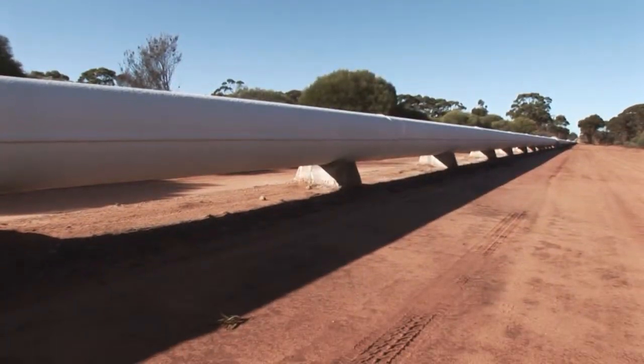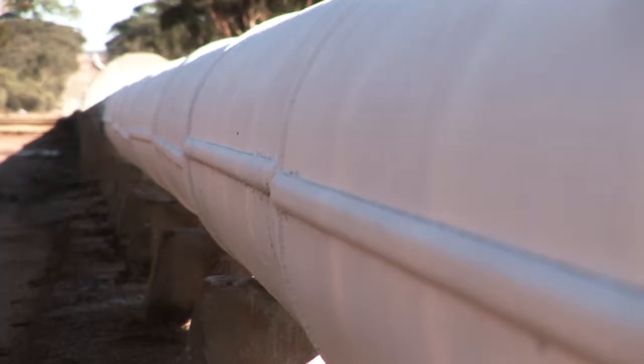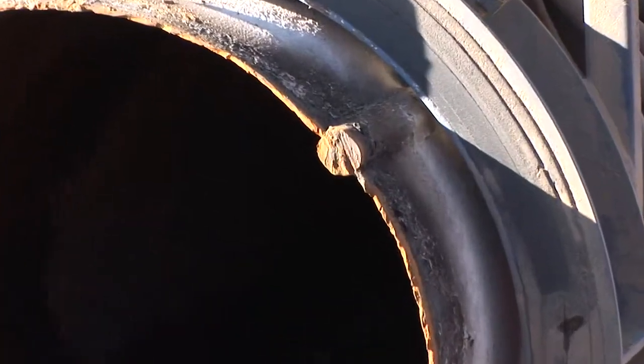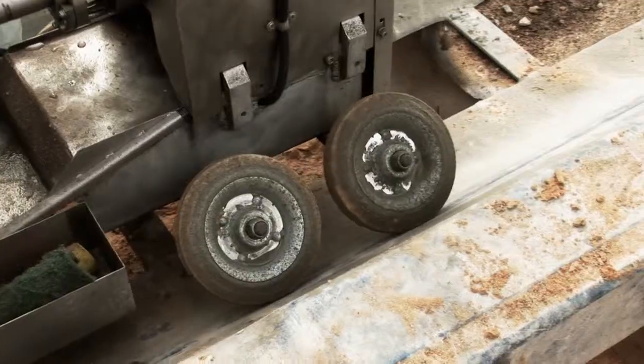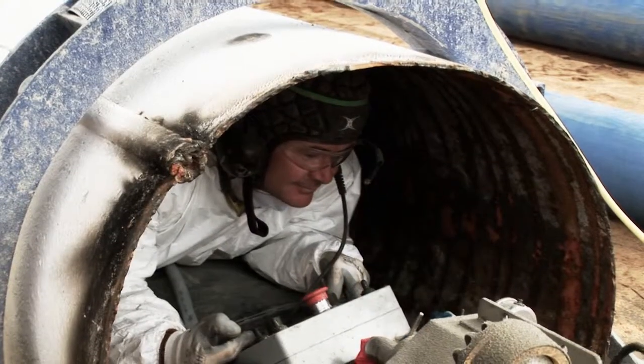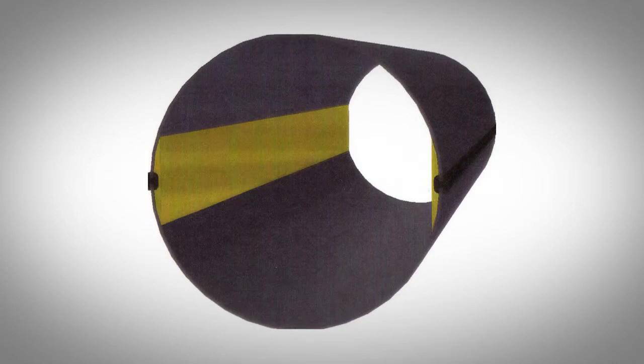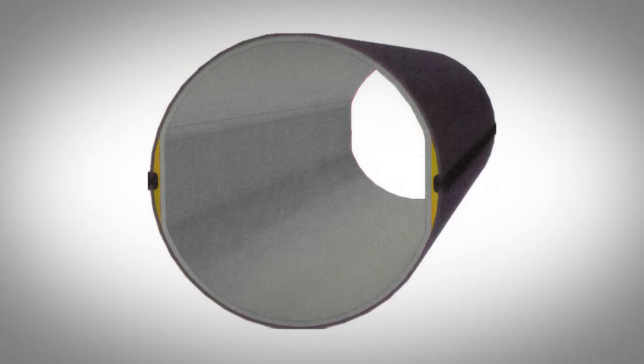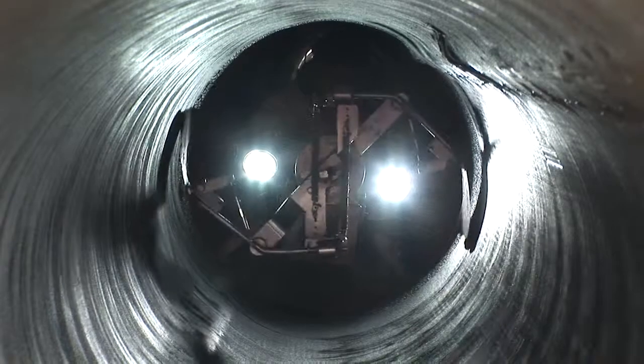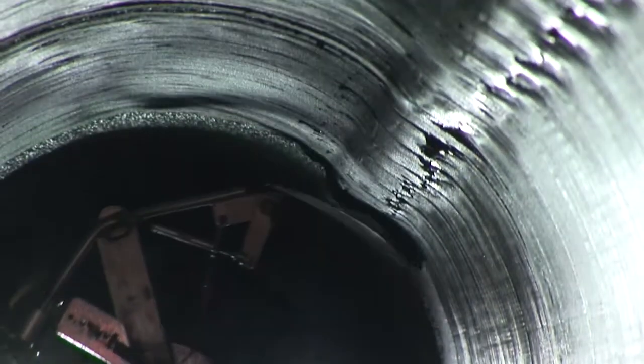The Goldfields pipe was manufactured using single sheets rolled into half-pipe sections and joined using a long locking bar. It is referred to as locking bar pipe, and an additional process called coving is required to prepare this type of pipe for relining. A fillet of cement mortar is sprayed over the internally protruding locking bar to fill the area between the bar and the pipe wall. This action prevents the formation of a shadow area that would otherwise result during the centrifugal lining process to follow, and it also assists the subsequent troweling operation.